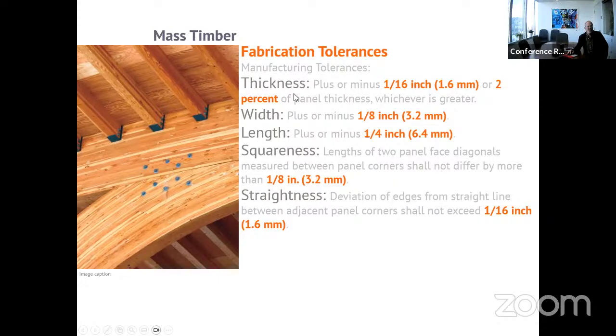More specifically, the thickness is within basically 2% of panel thickness, or about 1.5 millimeters. The width of the panel, about 3 millimeters. The length within 6 millimeters. The squareness, again, within 3 millimeters. And the straightness, again, within 1.5 millimeters. These are our standards for mass timber.